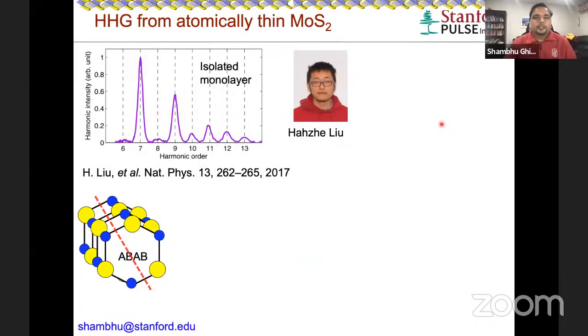This is the first observation of high harmonics from a monolayer MoS2. This was done by Hahzhe Liu, a former student in our group. Here, this is the crystal structure of MoS2 for the bulk. When you peel off the first layer and put it on a substrate, you observe high harmonics from that system in a single layer. In the bulk, there is a mirror plane, because every layer gets averaged over, and it has inversion symmetry. But when you take just a single layer out and put it somewhere, then you have some orientations where you actually break inversion symmetry, and you can see the signature in the form of these even-order harmonics. It's shown here.